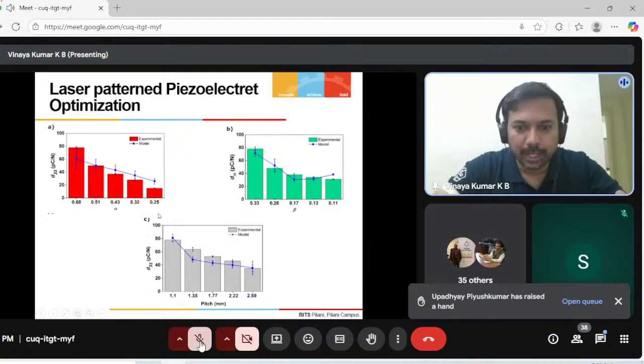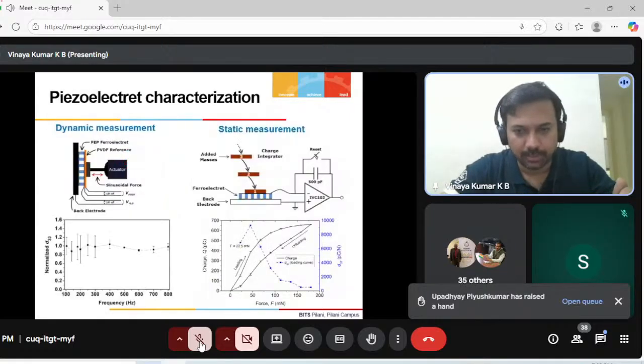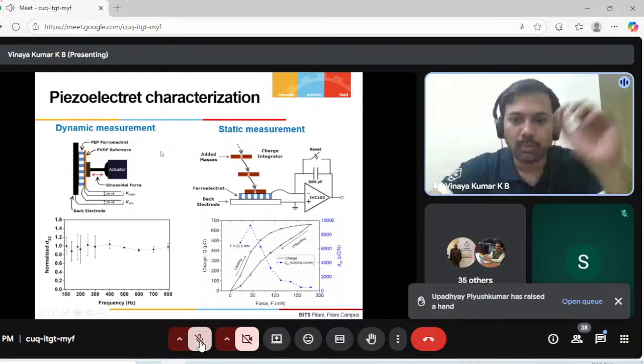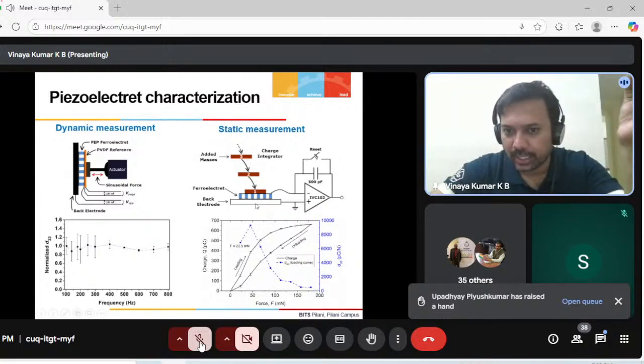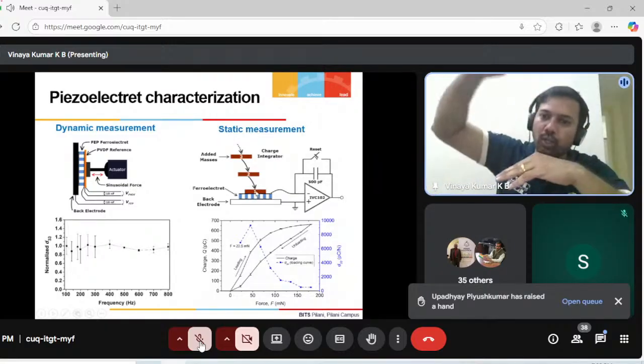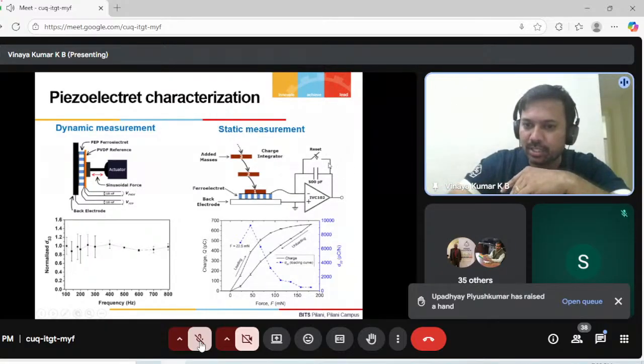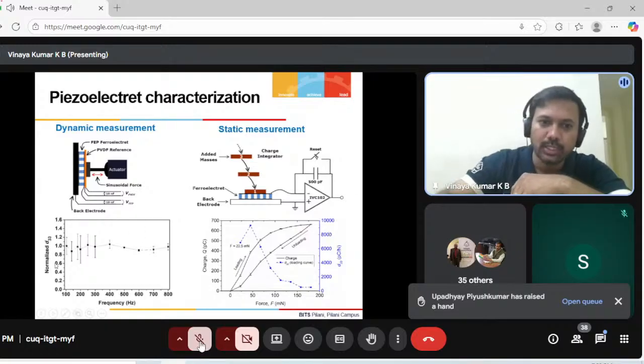Again, we're able to measure different parameters like alpha, beta, and the pitch, and understand how the piezoelectric coefficient, particularly the D33, varies with device performance. Normally people do a static measurement, which is very easy. You put the piezoelectric down, start keeping weight on top of it, and you measure the charge generation, right? And we also did the cycling. This is the charge generation, and this is the D33 of this one. We also did a dynamic measurement. So we used a dynamic actuator.